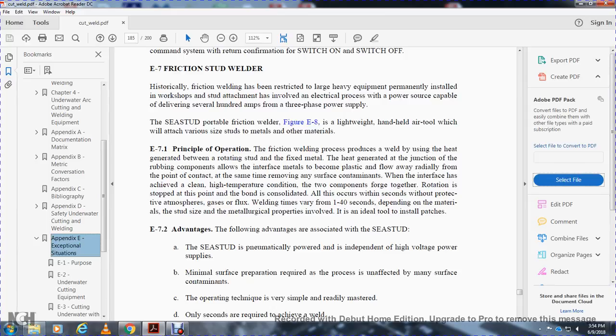E-7.1, principle of operation. In the friction welding procedure, the weld is produced by the heat generated between the rotating stud and the fixed metal. The heat generated at the junction of the rubbing components allows the metal interface to become plastic and flow radially from the point of contact, at the same time removing surface contaminants. When a clean, high-temperature condition has been achieved with the two components forced together, the rotation stops at the point where the bond is consolidated. All of this occurs within seconds, without protective atmosphere, gas, or fluxes.